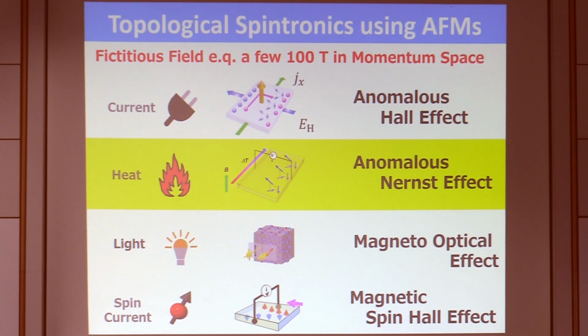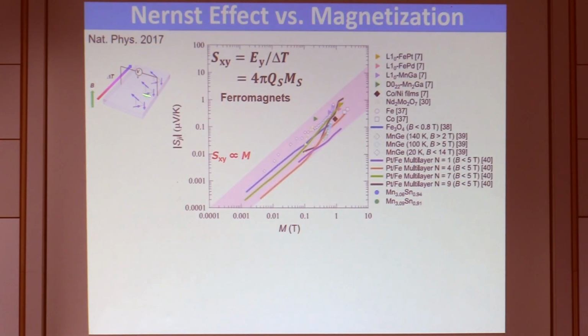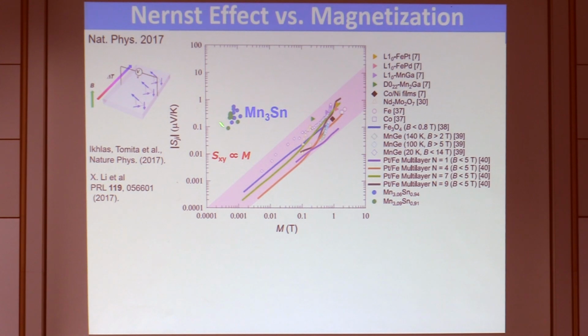Here comes the thermoelectric counterpart of the anomalous Hall effect. This figure has already been shown, and this is the plot for various types of ferromagnets for the Nernst effect versus magnetization. Again, a full logarithmic plot, and again, it's empirically known that they're proportional to magnetization. But if we locate Mn3Sn, according to this empirical rule, you are discouraged from measuring any anomalous Nernst effect. But when we measured this, it turned out surprisingly large.